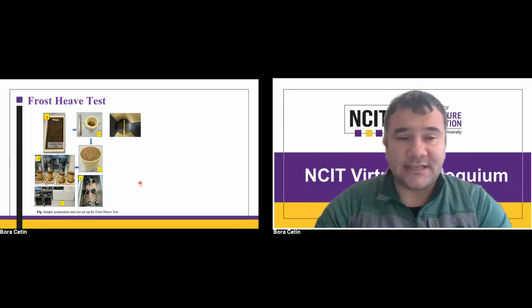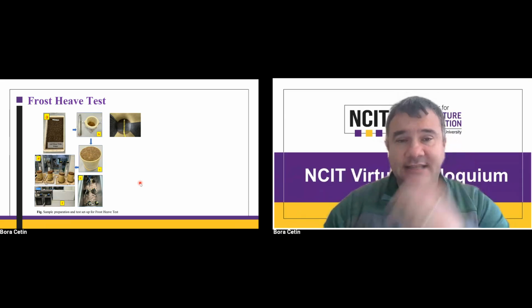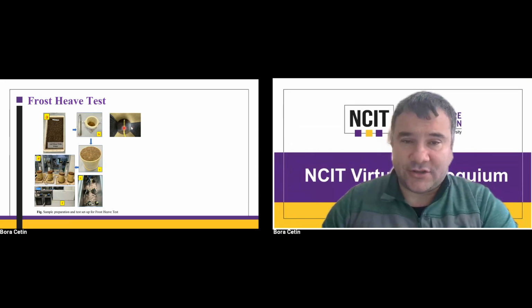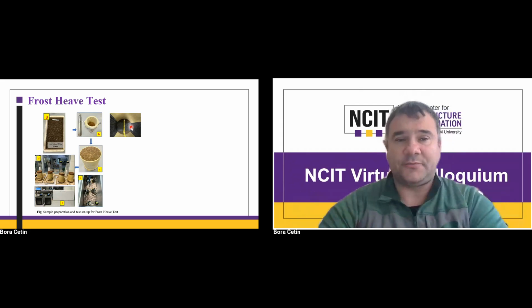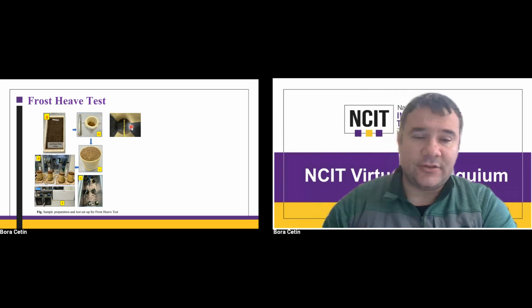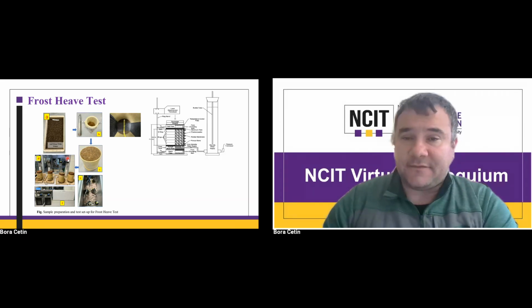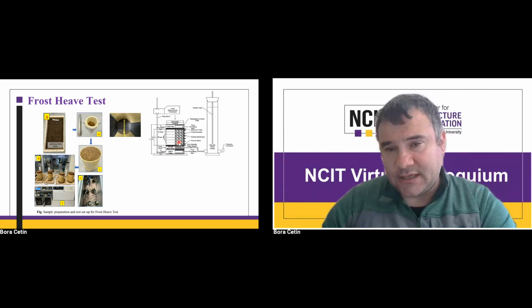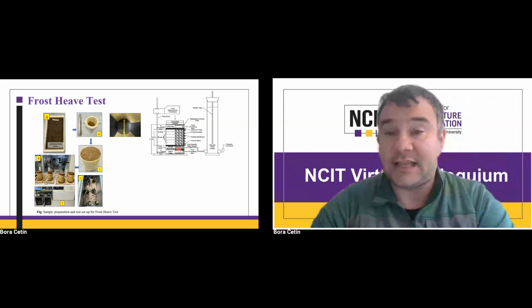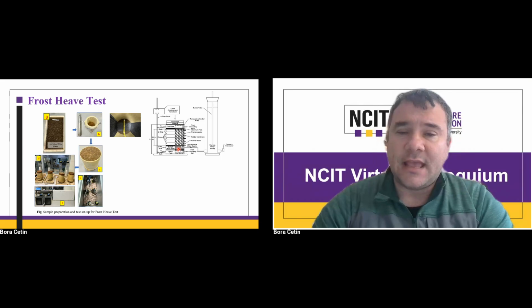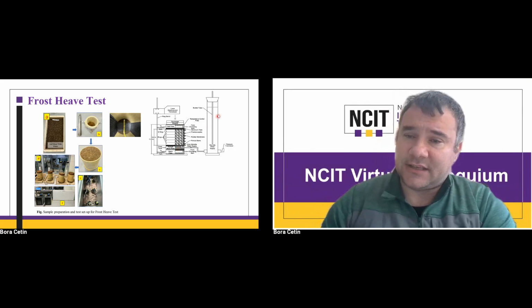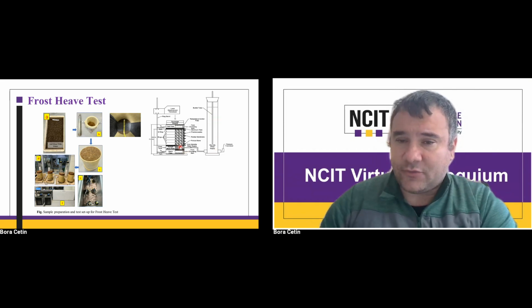We prepare our specimens 6 inches in diameter and 8 inches in height, and we sometimes put Wicking geotextile when we want to see the performance of the Wicking geotextile in this frost heave test setup. And we put thermocouples at every inch of the specimen and monitor it, and we have heat exchangers on the top and bottom to determine the thermal gradient that we apply to simulate the freezing and thawing of the samples. And we have a water supply simulating the groundwater table source.